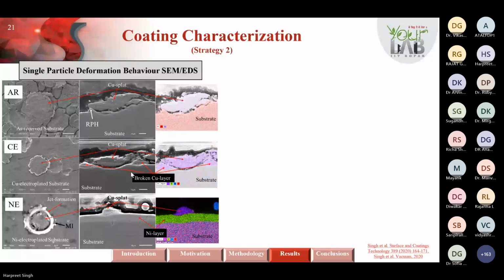So, okay, the copper electroplated substrate could not help us. This nickel, having good strength, did not get damaged, but the copper electroplated layer got damaged when we placed the copper powder over it by cold spray. What does it mean? It means if we have to recommend the right way of achieving adherence